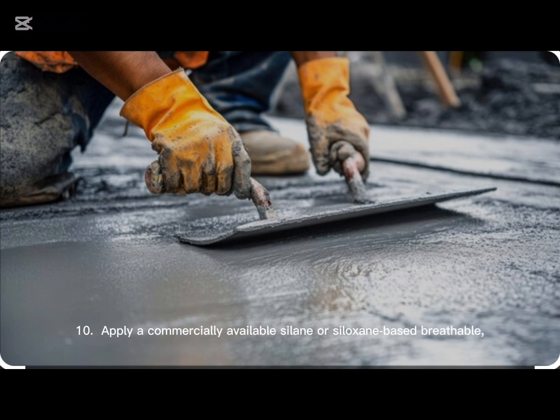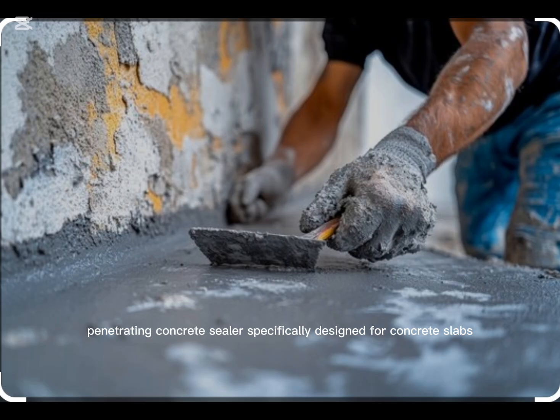10. Apply a commercially available silane or siloxane-based breathable, penetrating concrete sealer specifically designed for concrete slabs. 11. Do not use a jitterbug or vibrating screed with high slump concrete. 12. Prevent the addition of water when concrete is troweled or floated. 13. Curing should be done properly, for at least 7 days, and according to the number of days required. 14. Provide curing using a liquid membrane compound.